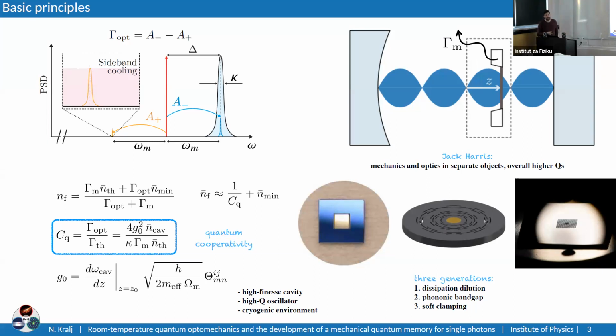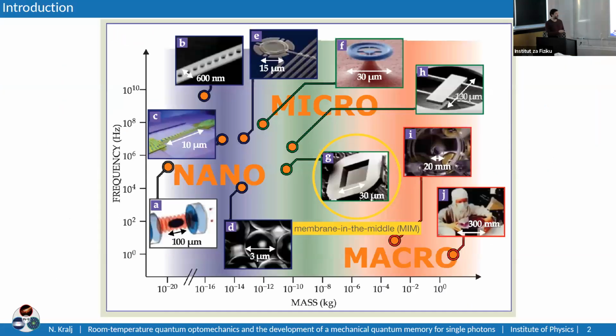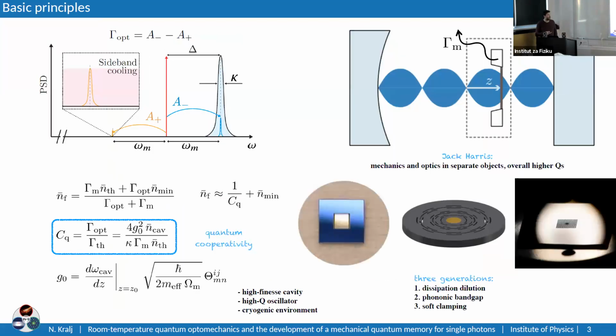The second reason is because it has very low intrinsic losses. And then I can tell you basically, in my mind, there are three stages of the advancement of the mechanical Q factors of such resonators that took place over, I don't know, the course of the last 15 years. They first started with membranes exactly like the ones depicted here. So this was commercially, I guess still is, commercially available by a company called Norcada, with Q factors of something like 10 to the 5 at cryogenic temperature, in ultra high vacuum.